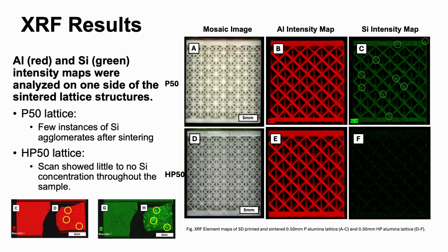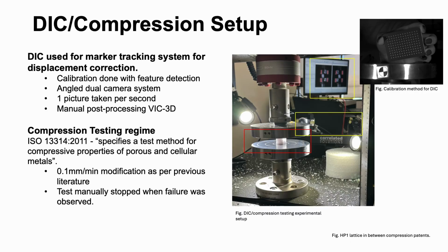Both aluminum and silicon maps were produced for both alumina purities, and the results showed that the 94% alumina has a pretty even distribution of silicon with a few instances of agglomerates, and the 99% alumina had very minimal silicon presence. Digital image correlation, or DIC, was used to track the actual displacement of the crossheads during the compression test.